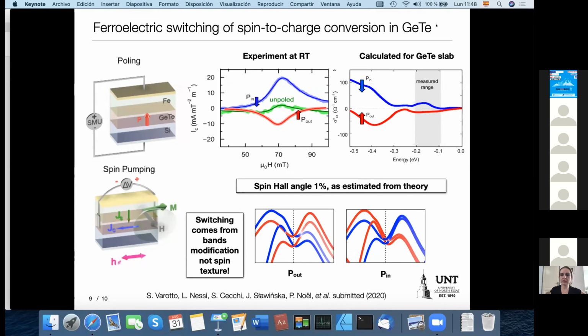Anyways, I was trying to explain that the origin of this switching is related to electric charges on the borders of the interface and the electric field inside. This is a mechanism that changes the band structure. So it's actually the change of the bands rather than change of the spin texture that contributes to this switching that was observed experimentally. And we have obtained a perfect agreement with experiments. So again, spin Hall angle is around 1%.